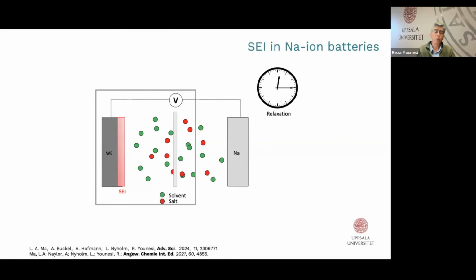So basically, we form SEI on the working electrode, then give it some time with no external potential or current, and we see part of this SEI dissolves back into the electrolyte, and we try to understand this. What you also see here is we have added a membrane between the negative and positive electrode.